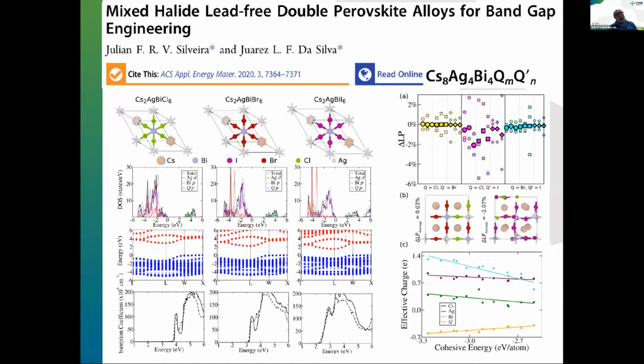We employ a cubic-like model in which you have 8 cesium atoms, 4 silver, 4 bismuth, and now 2 halide species. We exchange the composition of the 2 halides and explore all the possibilities, because we chose one small cell precisely to explore all the possibilities. From that, we could come up with nice models and understand what is happening in the double perovskites. Here I show one important point: the competition between stability and band gap, the electronic properties. If you improve stability, you lose the band gap properties in the direction of photovoltaic applications.